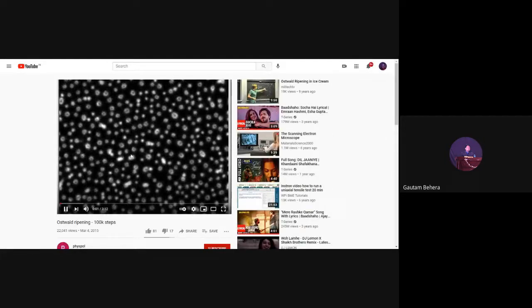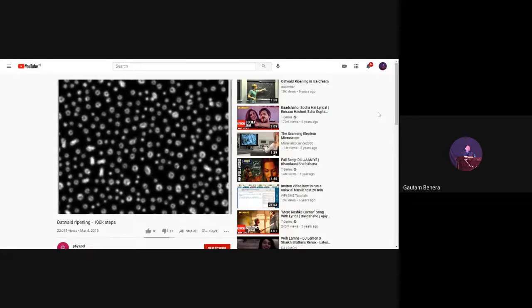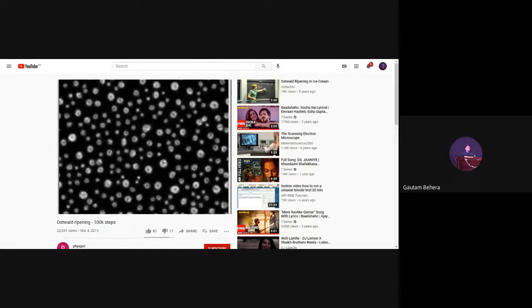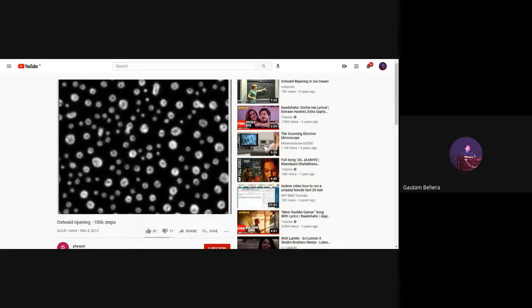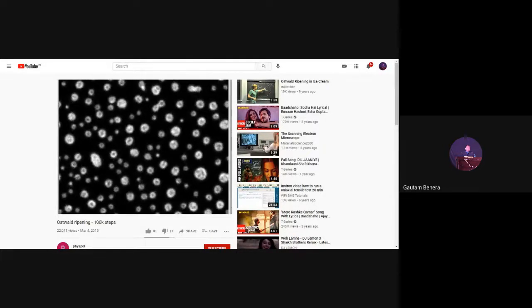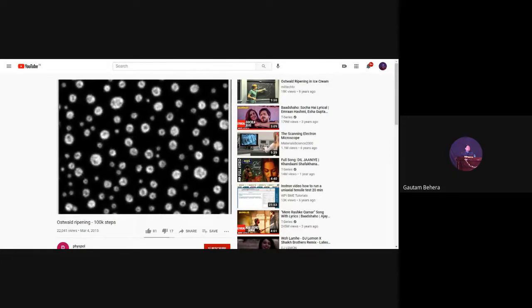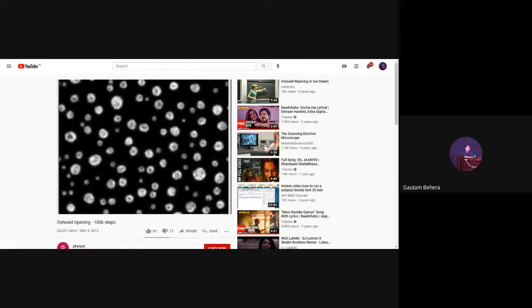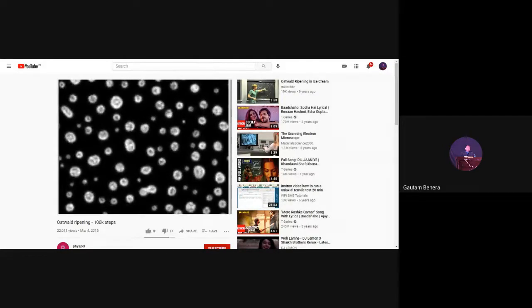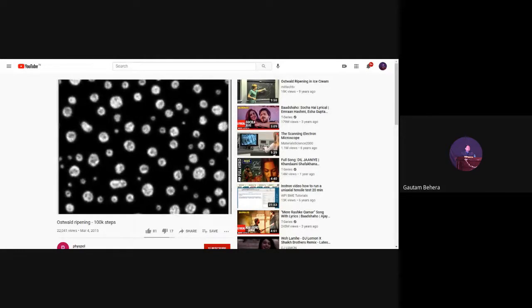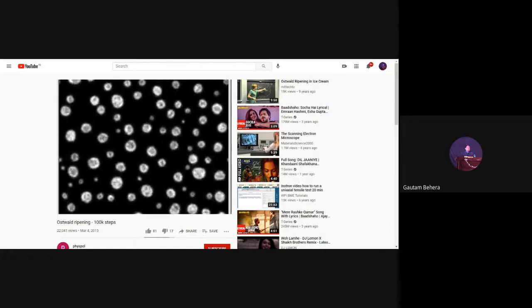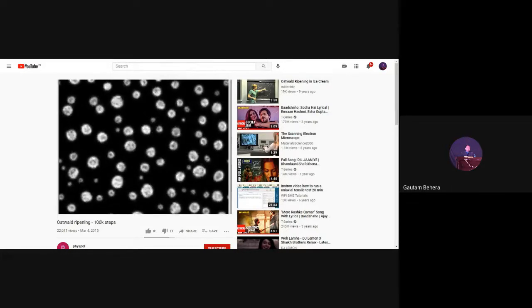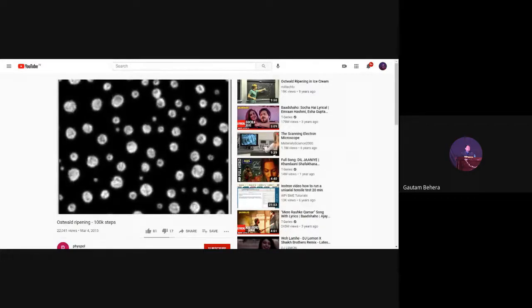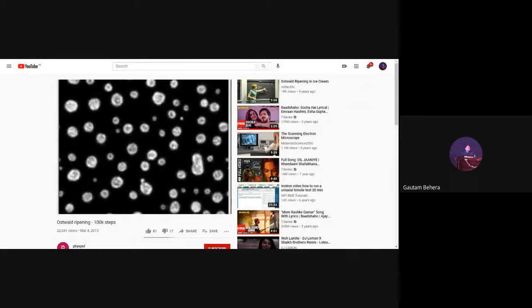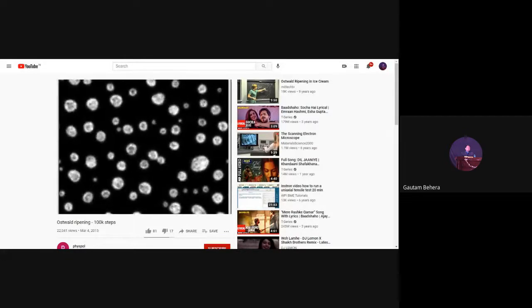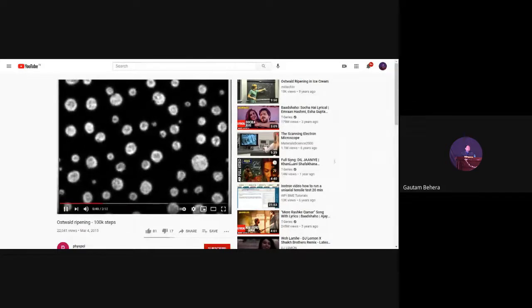Look at another video. Just look at the smaller particles and bigger particles. Carefully look at the bigger particles and smaller particles. You can see that the bigger particles will become more and more bigger with time, whereas the smaller particles will get disappeared. Can you see the bigger particle is engulfing the smaller particles and it is becoming bigger, and the smaller particle is getting disappeared. So what will happen at the end of the time? You will be having bigger particles. See, the bigger particle is becoming more bigger with time.